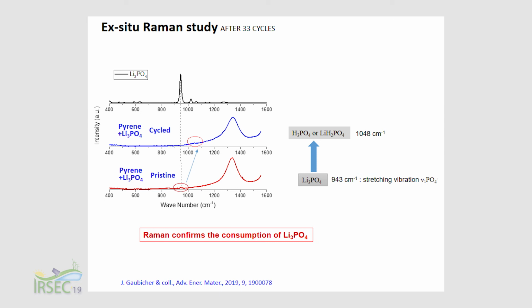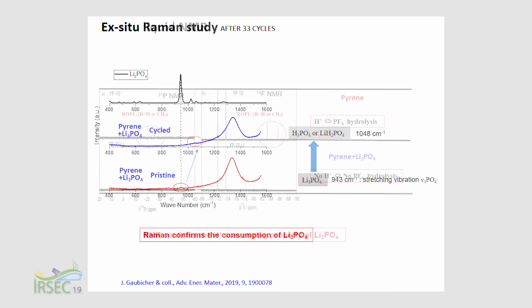We have done also Raman studies. In pristine electrodes with the two additives, we can see a vibration signal characteristic of Li3PO4. And in cycled electrodes, we do not have this signal anymore. It means confirmation that Li3PO4 is consumed after first charge.